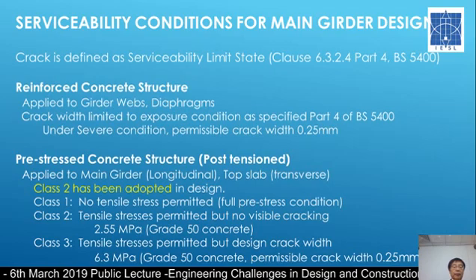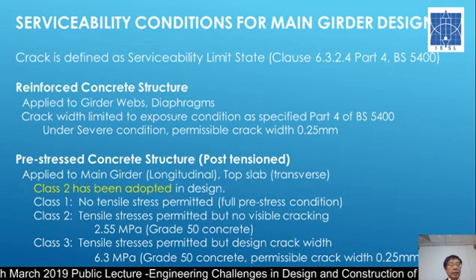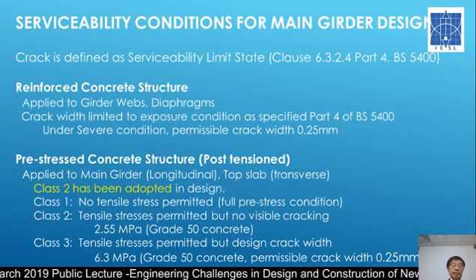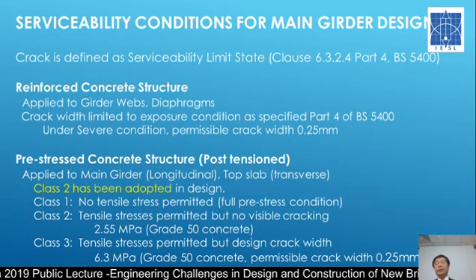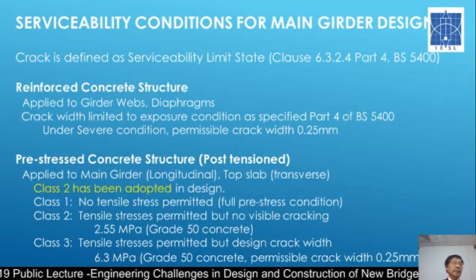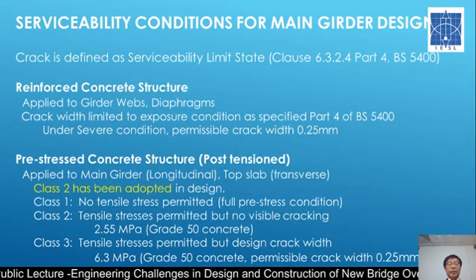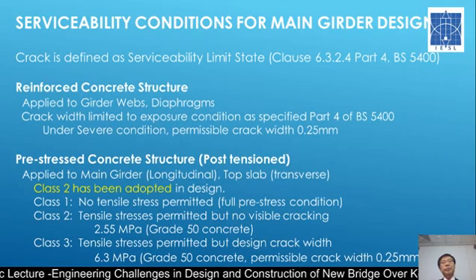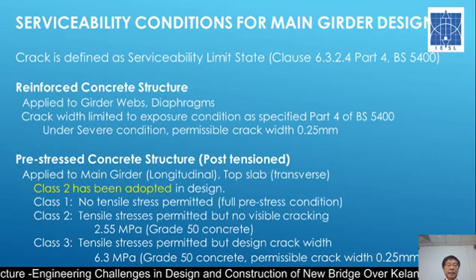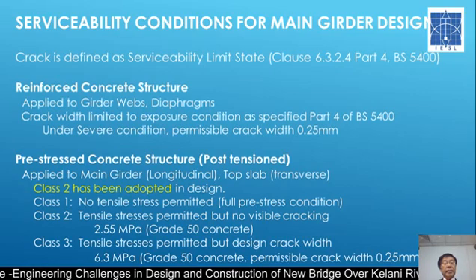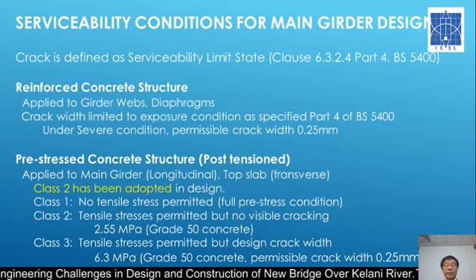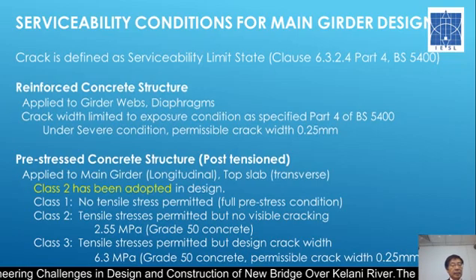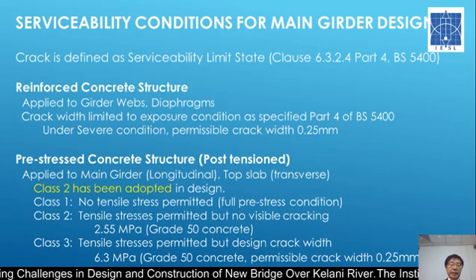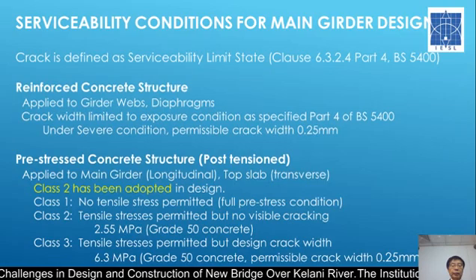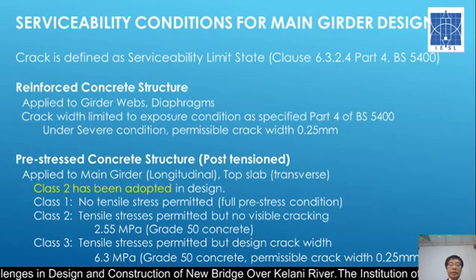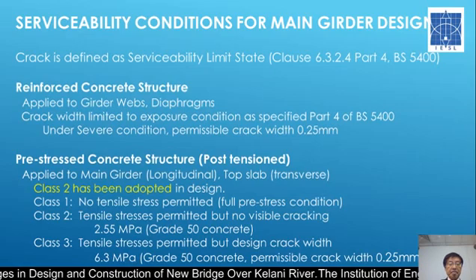For the design, we have some factors that we have to consider, especially serviceability. Because reinforced concrete theoretically has cracks, we have to minimize or limit the crack width. The BS 5400 standard gives an allowable crack width, and we have used 0.25 millimeters, which is allowable for the design.